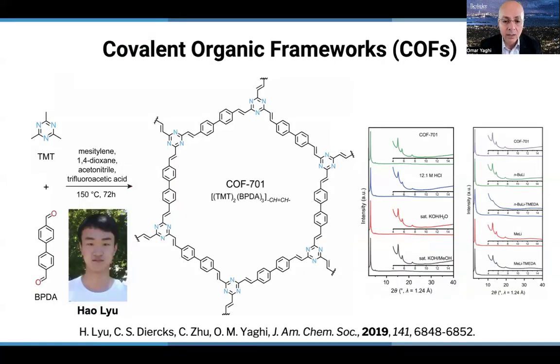And there, if you want to do this DAC, you need to go to COFs. And in COFs, you see here back in 2019, we had a breakthrough in that we can make COFs that are made from some of the strongest bonds known in chemistry, carbon-carbon bonds, carbon-carbon double bonds, and carbon-nitrogen double bonds. And you can see here on the right the stability of this material in highly concentrated HCl, in acidic media, in concentrated basic media, as well as corrosive media such as n-butyllithium, methyllithium.